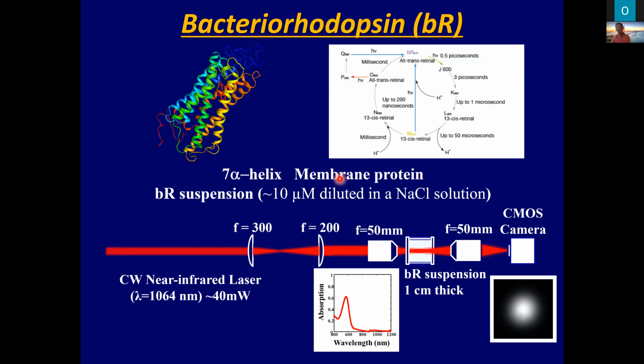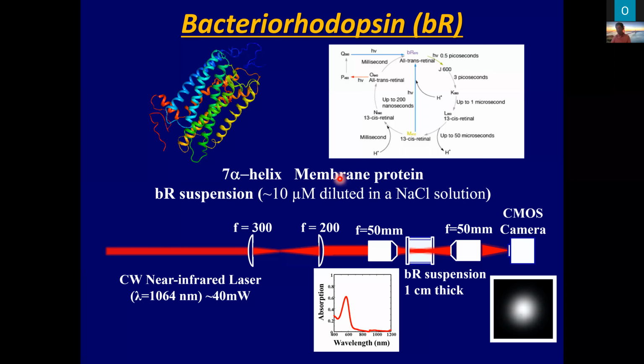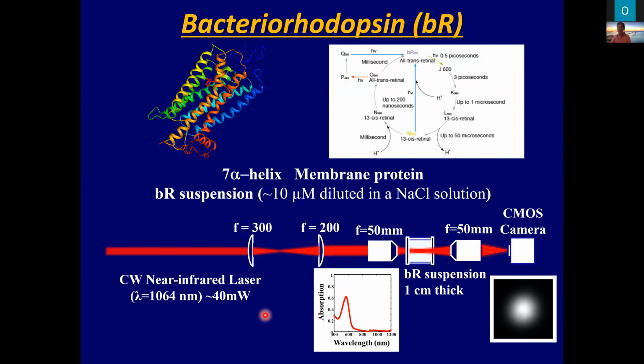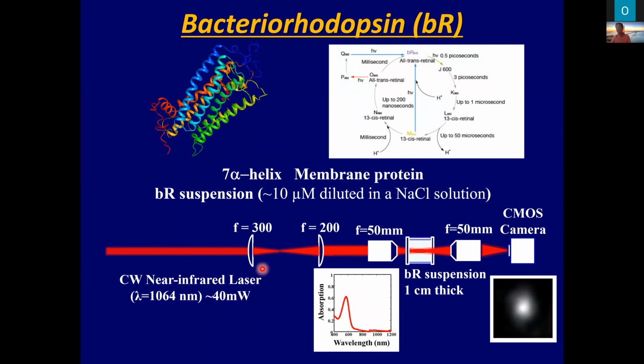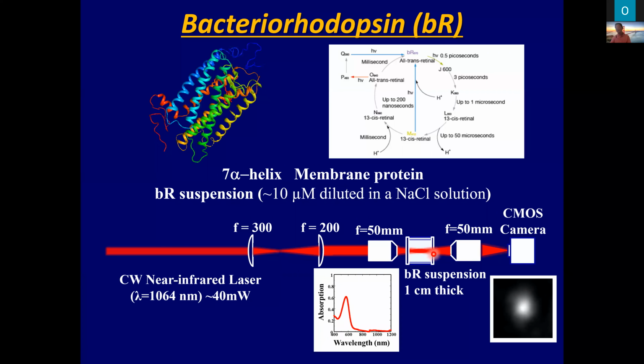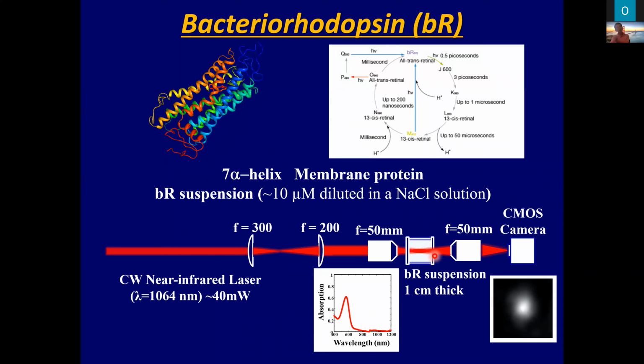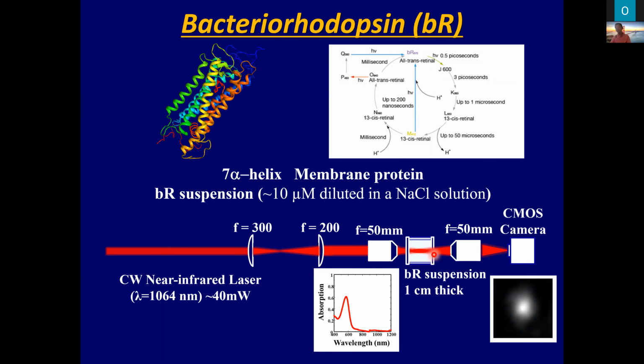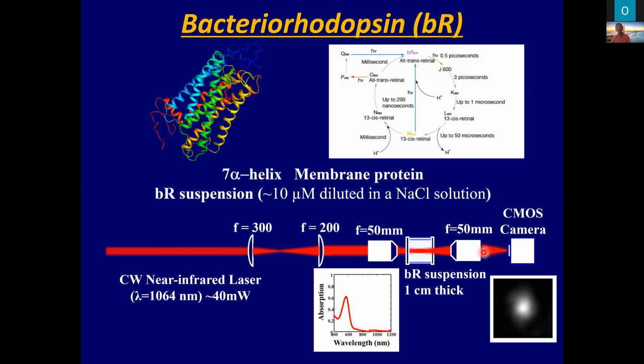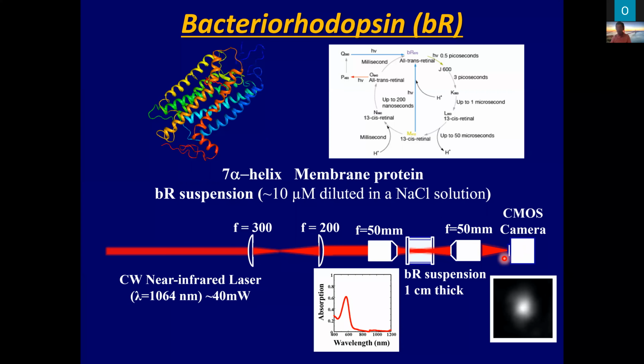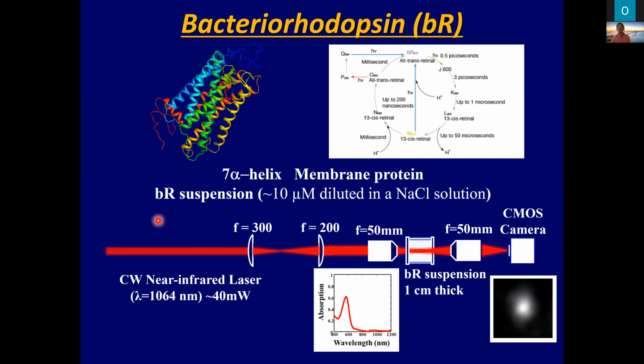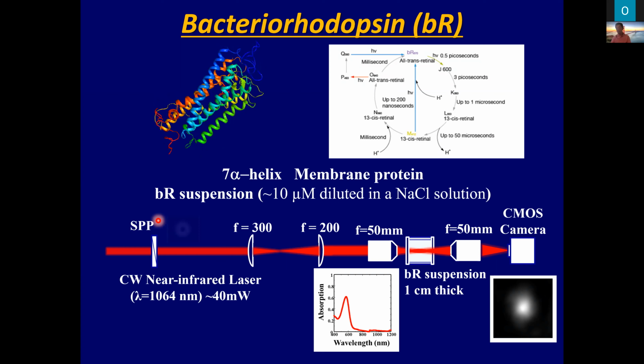At first, we inject a Gaussian beam. This is a self-focusing effect. The laser beam passes through the bacteriorhodopsin suspension. The self-focusing effect happens. A small spot is observed on the CCD camera. We convert the Gaussian beam to the optical vortex by using a spiral phase plate. What happened? Quite interesting.